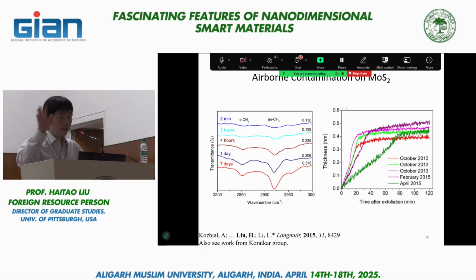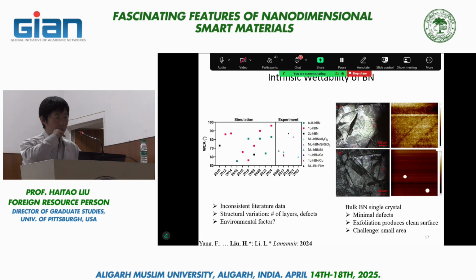So we recently started to do measurements on bulk single crystal boron nitride, and those are grown by a high temperature process. You can get millimeter-sized single crystal boron nitride. It's a very difficult experiment because we have to work with a very small area, and you see the kind of structure shown here. The AFM image shows a very high quality surface, but if you look at the optical image, there's still a lot of fracture on the surface, so it's not the ideal system, but still one of the better systems we can use.